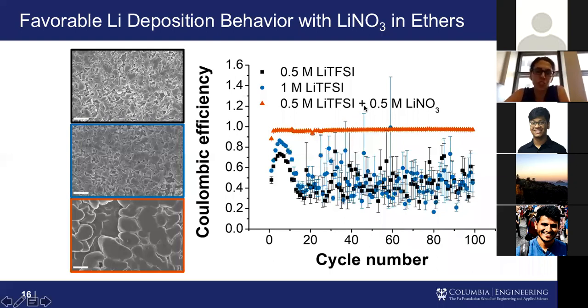But if we change up our salt composition a little bit and we add about 50% of this original salt, this lithium TFSI, and 50% lithium nitrate, it completely changes the game. We get these very low surface area structures that don't show any sharp features, and we get very high Coulombic efficiency. We're right around 98% for 100 cycles, which is very impressive for a battery electrolyte. So what is this nitrate doing in our electrolyte? How's it changing our electrolyte decomposition pathway compared to the normal TFSI sample?